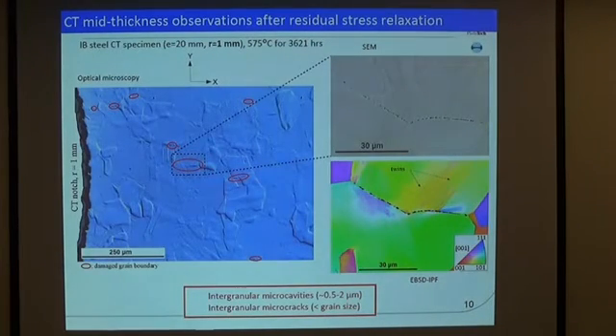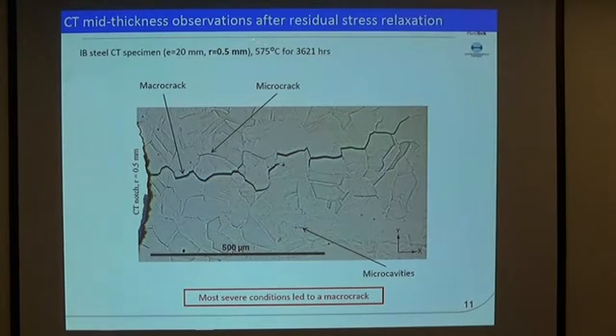So when you take the sample out of the oven and you cut here is the former notch root radius and in this optical micrograph you can see the height of the grains and on some grains you find carbides and voids. This is the second steel for a notch root radius of one millimeter and this aging time and temperature. So we have two grains and along the grain boundary we see voids. Typical creep voids. For another condition a notch root radius of 0.5 millimeter we actually really see a crack. So there must be some influence of the severity of the notch on the development of the phenomena.